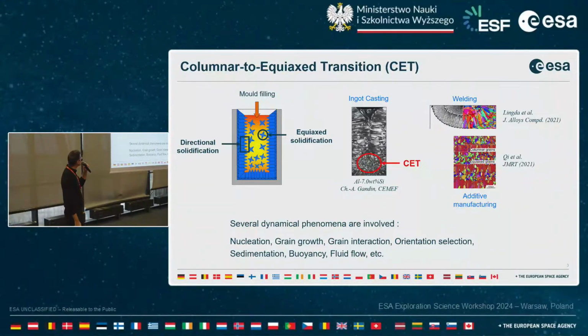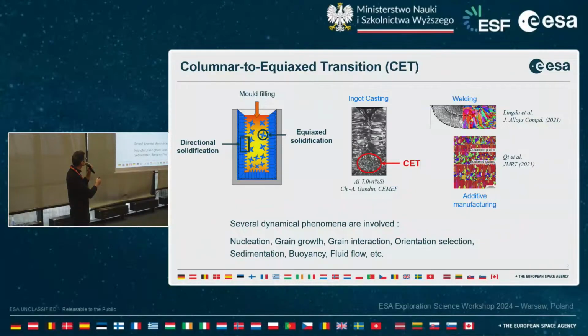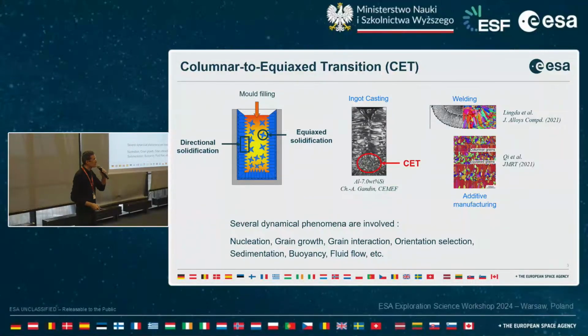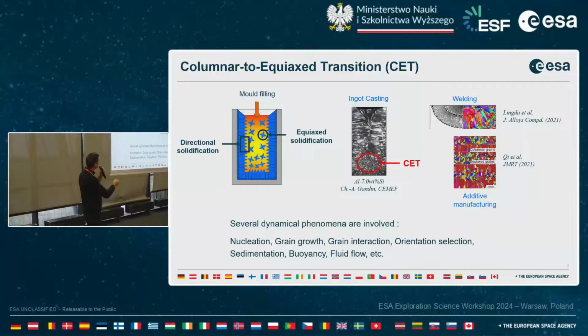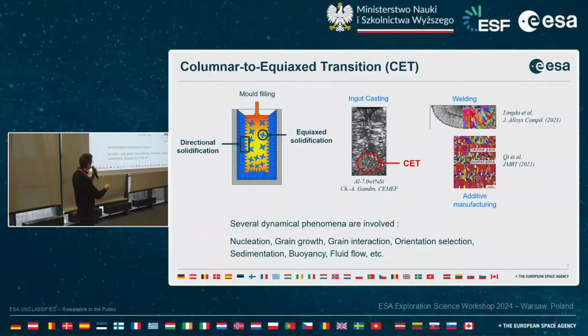So, the columnar to equiaxed transition occurs when you have dendritic grains that developed in a preferred direction, and when these grains are stopped by grains that developed in an isotropic manner, so-called equiaxed grains, you have a transition from columnar to equiaxed grains, a columnar to equiaxed transition. This feature is well known to occur in casting, as you can see here in this picture, but it also can be found in other processes, such as welding, and even more complex processes, such as additive manufacturing, as illustrated over here.